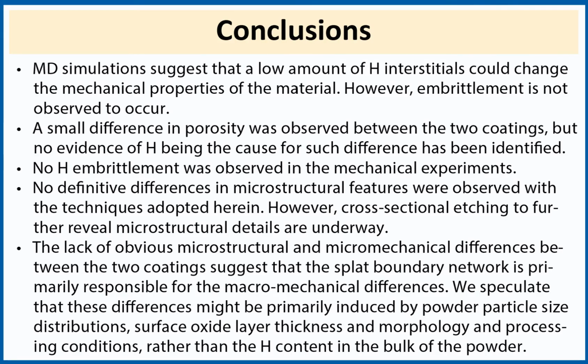In conclusion, besides the small difference in porosity percentage, no definitive differences in microstructural features or evidence of hydrogen embrittlement were observed with the techniques adopted so far. The lack of obvious microstructural and micromechanical differences between the two coatings suggests that the splat boundary network is primarily responsible for the macro-mechanical differences.